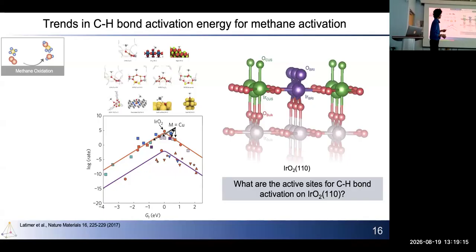Here's what the surface of iridium oxide looks like, and you have different species here. You have what we call the coordinatively undersaturated oxygen, or the CUS oxygen, and we have a bridge oxygen. They're just differently coordinated oxygens on an iridium surface, and then of course you have the corresponding iridium atoms as well. Now the question is, which one of these species is responsible for the high activity that was predicted in the theoretical modeling exercises?